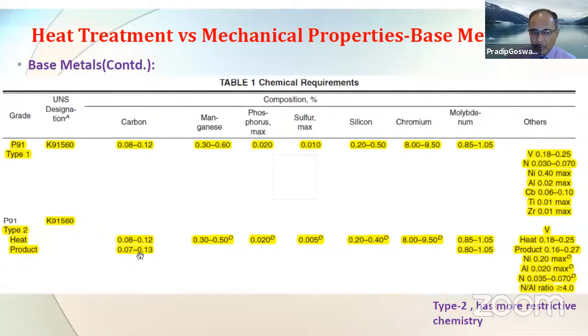Generally speaking, type 2 is recommended for applications where creep and enhanced high temperature properties are more of a consideration. That means there is a category like supercritical and subcritical boilers. Now, for subcritical boilers, if somebody wants to use P91 material, the choice would be type 1. But if it is a supercritical boiler, typically the designer has the flexibility to go with either type 1 or type 2, depending on the specific design considerations.